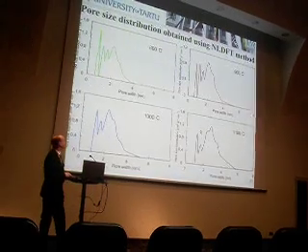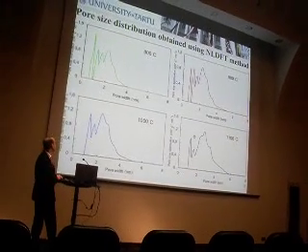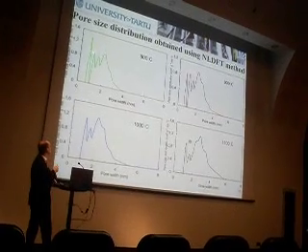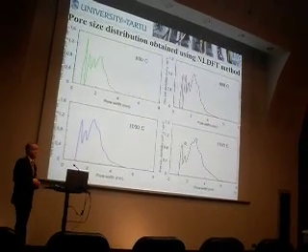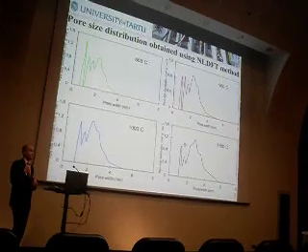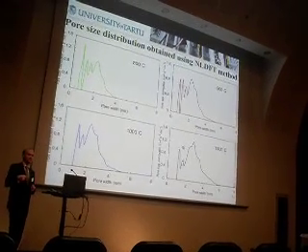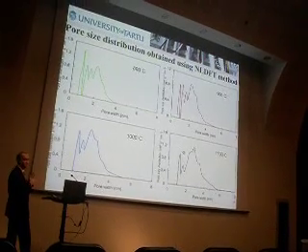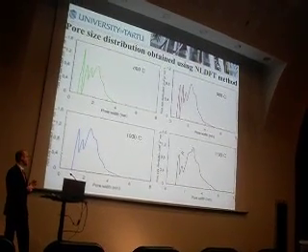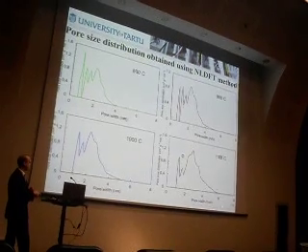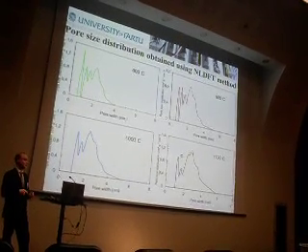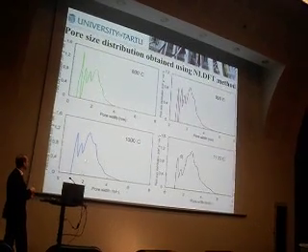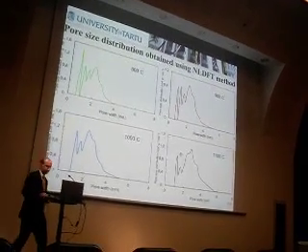And also, when we look at the pore size distribution, then we can see that the material has narrow pores, but it also has some mesopores. And as we increase the synthesis temperature, the average pore sizes tend to shift a little bit to the wider pores. The shift is not very large, but it is still noticeable.